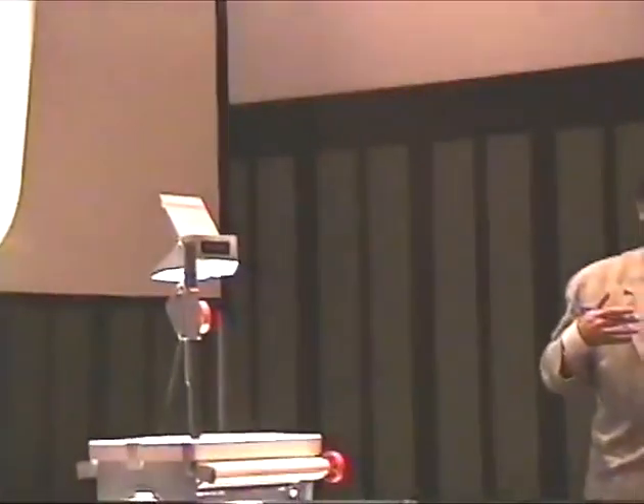These two peaks change in size depending on the cobalt-copper content. Namely, the peak at the lower temperature increases in size as the copper content increases, whereas the higher temperature peak decreases in size as the cobalt content decreases. So this trend suggests that the lower temperature peak is related to the reduction of the copper oxide phase, whereas the higher temperature peak is related to the reduction of the Co3O4.